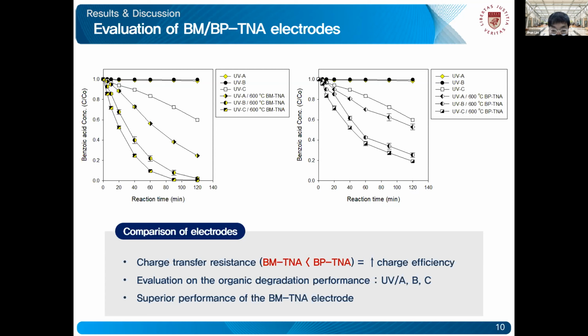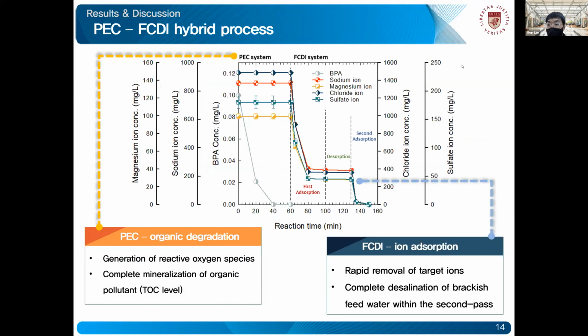And also for the quality of the output water product, from the final presentation slide, as you can see, the organic is completely zero, and that's by TOC standards, not the exact concentration of the material itself. And on the ionic part, we can see just running the first pass of the FCDI system removed almost 80% of the entire ion, and having the second pass removed 100%. So if we operate the second absorption phase, actually the concentration of the ion is zero.